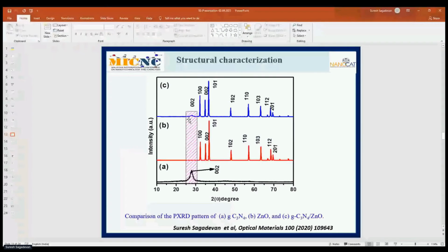You can clearly see that we observe a sharp peak at 27.4 degrees for the graphitic carbon nitride sample. It corresponds to the interplanar stacking peak of the aromatic structure, the interlayer structural peak. This peak infers the crystallinity of the sample. You can see the zinc oxide peaks, the well-known peaks. We observe high crystallinity of the sample, and also each peak corresponds to the single phase of zinc oxide.